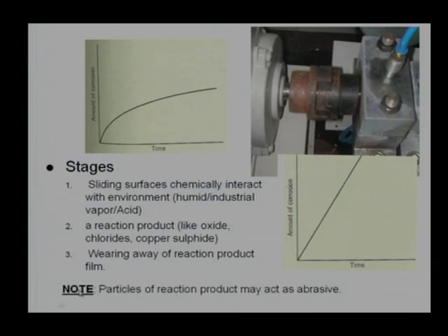Now, one point to be noted is that these particles, which are getting removed from the surface, iron oxide, may act as an abrasive material, and finally cause damage to the material due to abrasive wear. As I mentioned in the last lecture, abrasive wear failures are the maximum. Wear occurring due to abrasive wear is the maximum. Interestingly, adhesive wear also leads to abrasive wear. Corrosive wear also leads to abrasive wear. The final destiny is the same, but the initiation mechanisms are different.